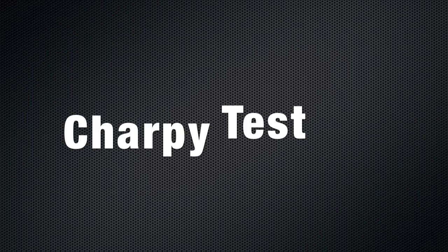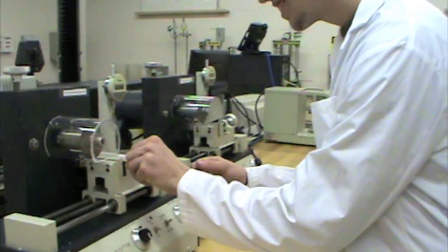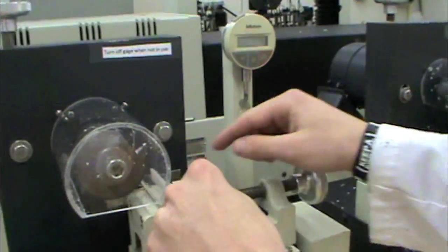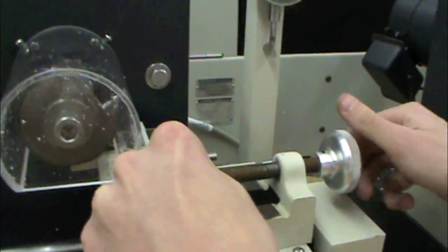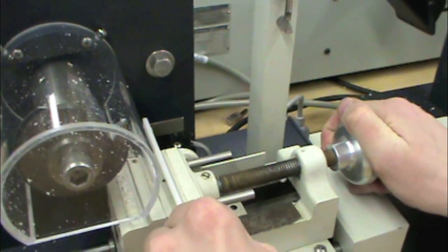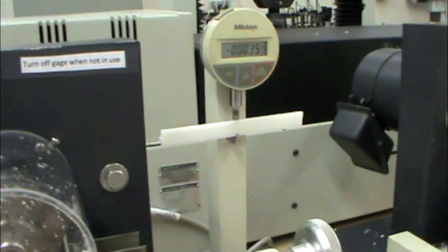Now that you are done with the Izod impact test, you are now ready for the Charpy test. You will be using a 5-inch test specimen for the Charpy impact test, and will be notching them in the same manner as you did the Izod notch sample, but be sure to use the larger guide so the notch is in the center of the specimen. Also measure the material remaining in the same manner. All Charpy specimens are notched.